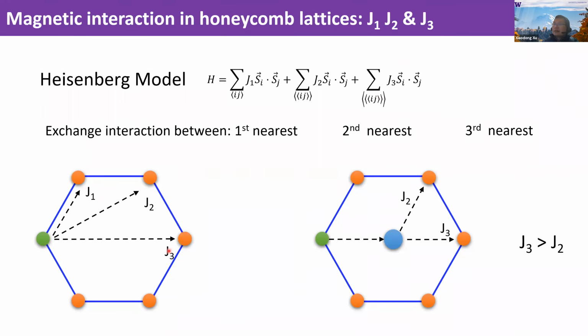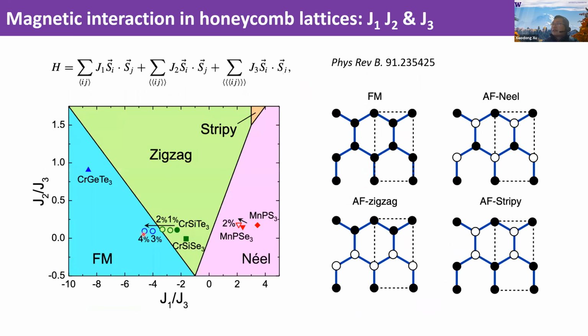It depends on the ratio of these J1, J2, and J3. The system can behave very differently in terms of magnetic order. My collaborator Dixiao calculated the phase diagrams as a function of the ratio of J1, J3, and also J2, J3, showing these plots here. For example, in this bottom left corner, we get the ferromagnetic order.